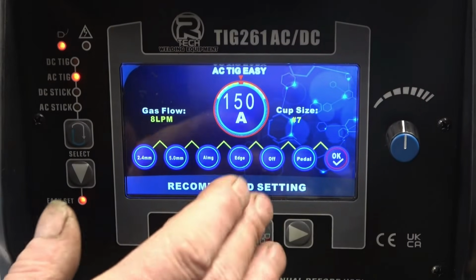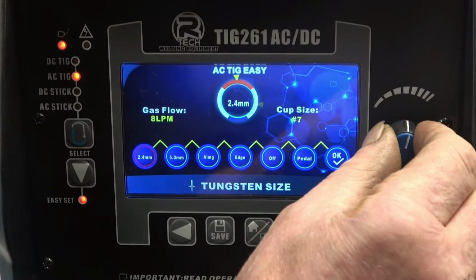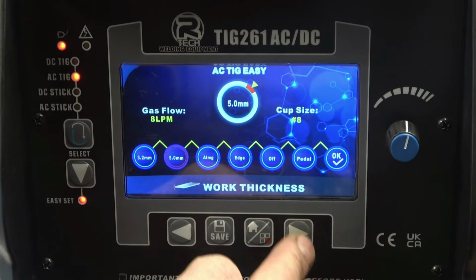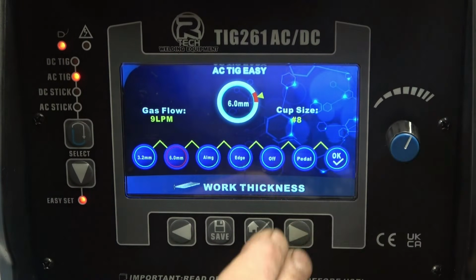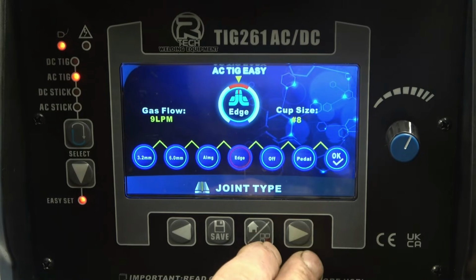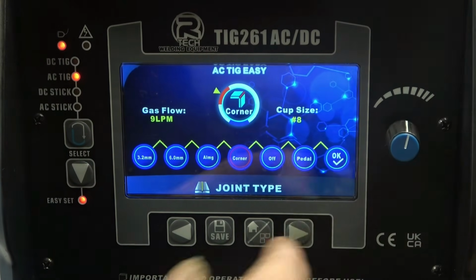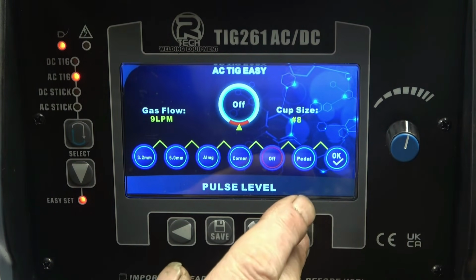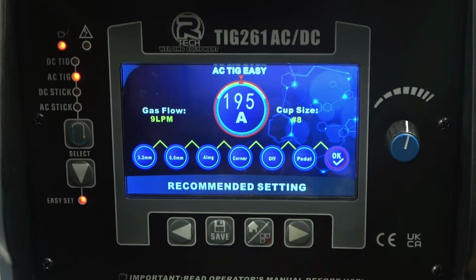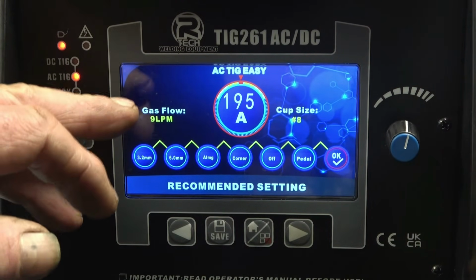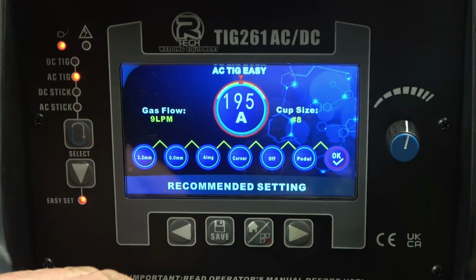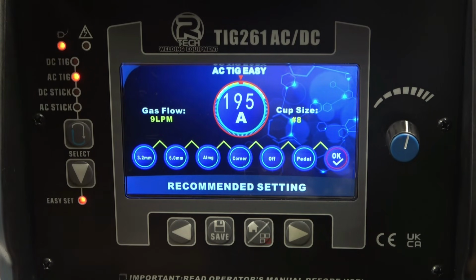I'm going to go up to 6mm now, so we need to go to 3.2mm tungsten. 6mm. We'll do a corner weld, pulse off on a pedal. Right, so it's asking for 9 litres a minute argon. It's going to give us 195 amps as a starting point with a number 8 cup. That's why I've gone to a 3.2mm tungsten, a 2.4 wouldn't stand that sort of amperage for any length of time.